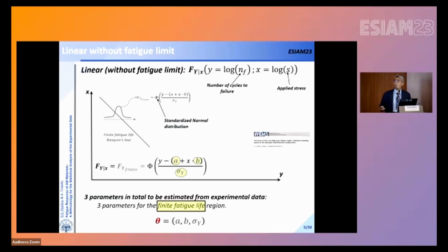That depends on the applied stress through the Basquin law and on the scatter of the experimental data. In total, for this very simple probabilistic SN model, we have three parameters. So the set theta of the parameters that must be estimated when applying the statistical methodology that I will describe later are three in this case.